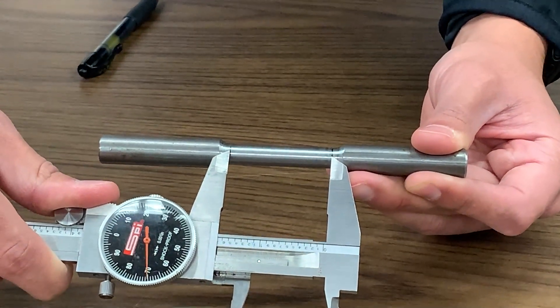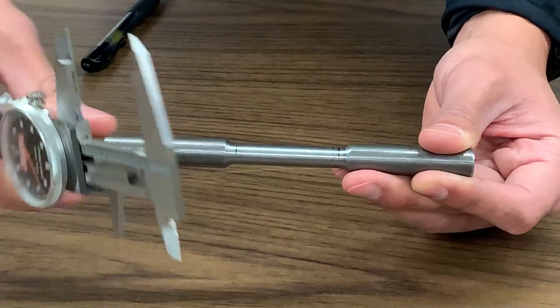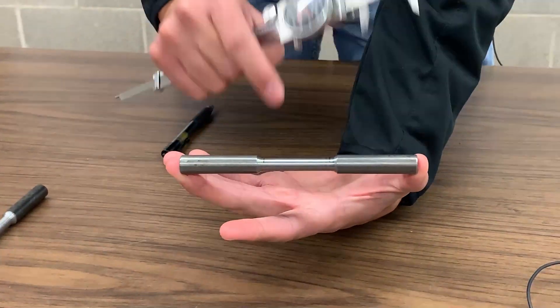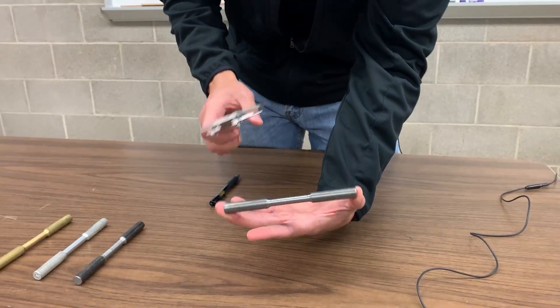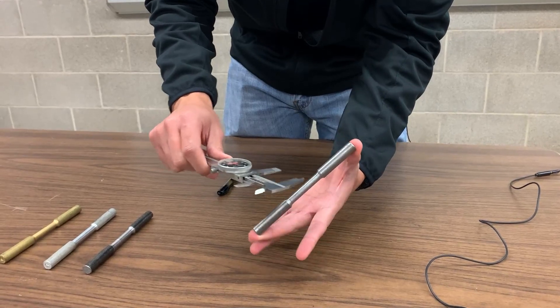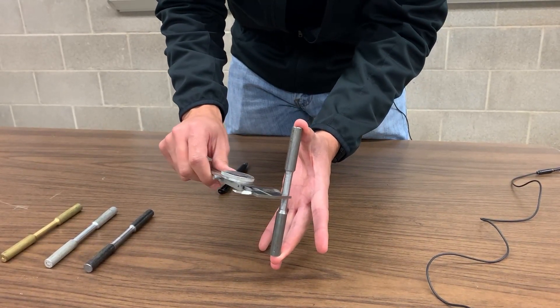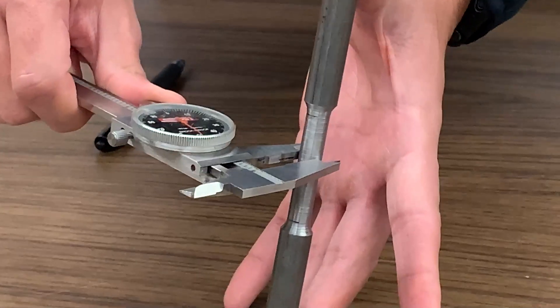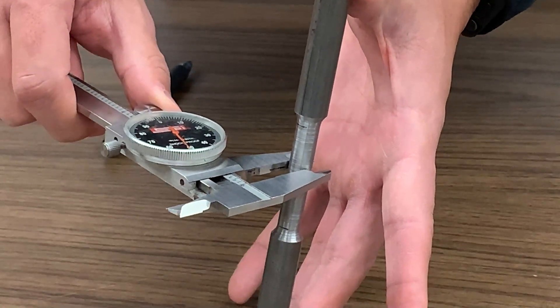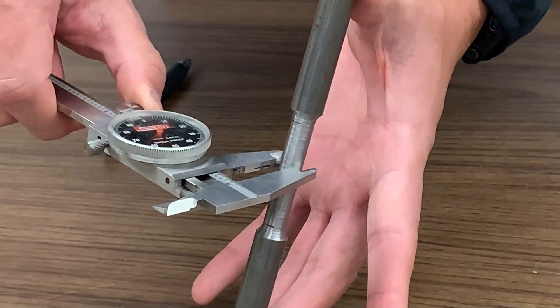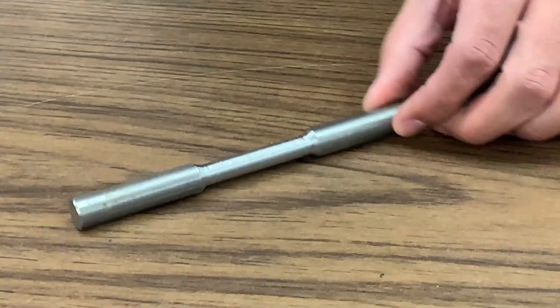I'm going to place my calipers at those two markings and take their reading. Once we perform the test, we're going to have to obtain that gauge length again, so the markings will be helpful later to be consistent. We can use our calipers to measure our diameter — making sure to obtain the measurement using the tips of the prongs and not the back portion where there's a gap.